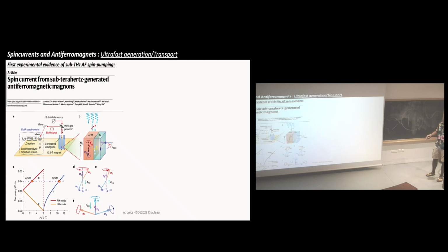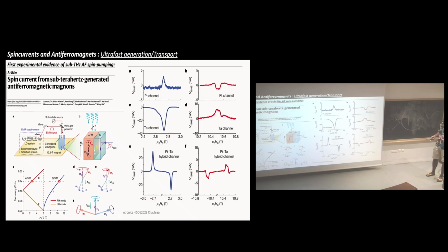And what's happening, as I said before, in Cr2O3, you reach the spin flop, and after the spin flop, you have the quasi-ferromagnetic resonance, and this time, so you go from here to here, and now you don't rotate, you rotate but 90 degrees to what it was previously in the normal phase. And this is what they measure.